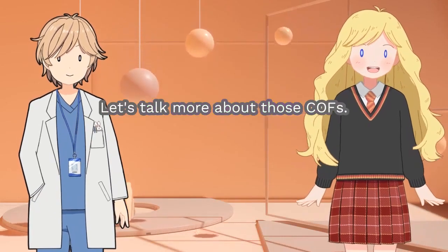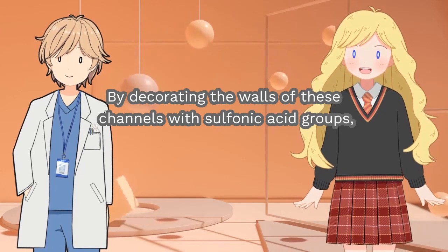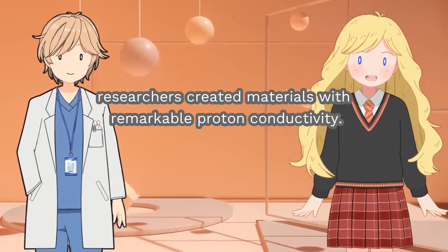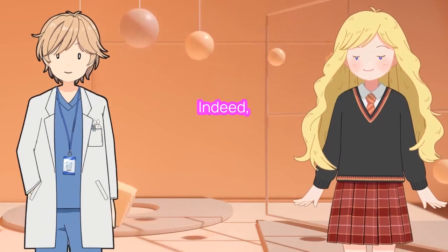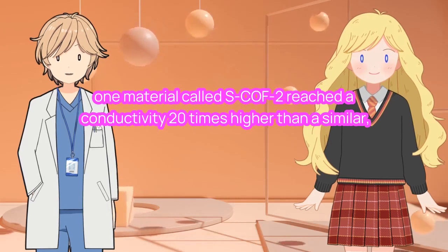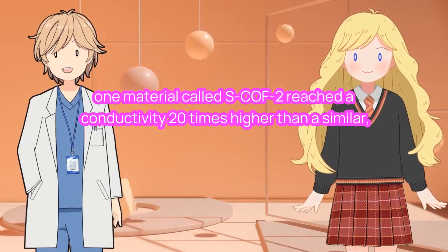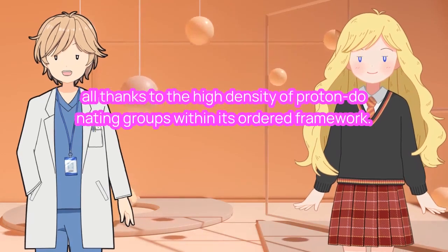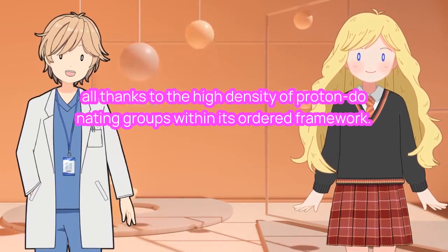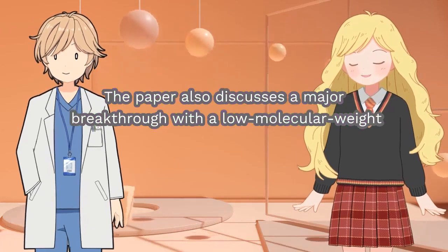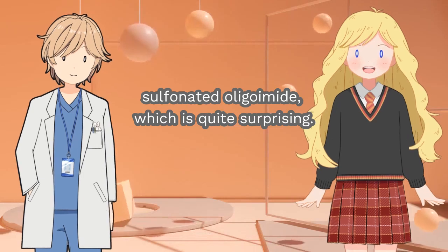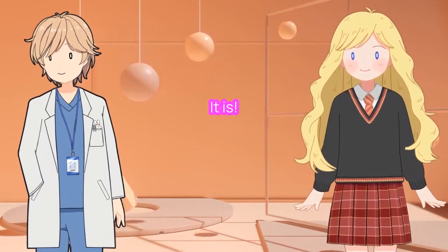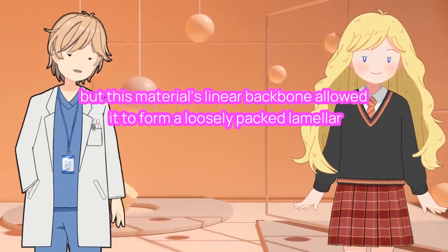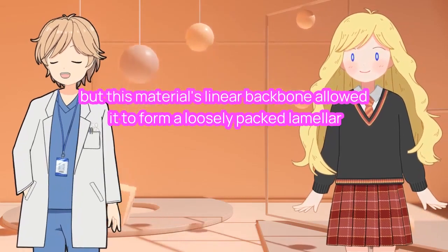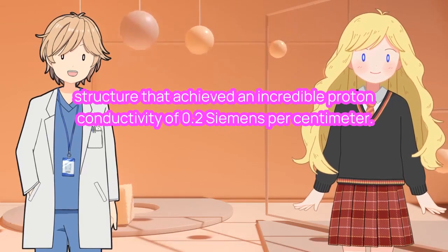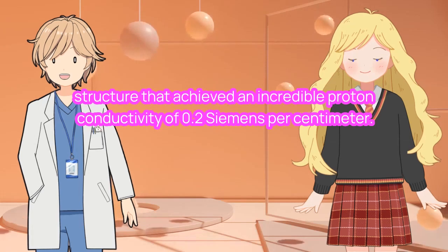Let's talk more about those COFs. By decorating the walls of these channels with sulfonic acid groups, researchers created materials with remarkable proton conductivity. Indeed, one material called SCOF2 reached a conductivity 20 times higher than a similar, less acidic version, all thanks to the high density of proton-donating groups within its ordered framework. The paper also discusses a major breakthrough with a low molecular weight, sulfonated oligoimide, which is quite surprising. It is. Usually, you need long polymer chains, but this material's linear backbone allowed it to form a loosely packed lamellar structure that achieved an incredible proton conductivity of 0.2 Siemens per centimeter.